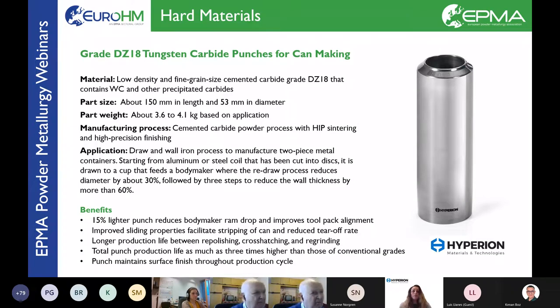This case study corresponds to our cemented carbide solution for manufacturing two-piece beverage cans via drawing and ironing of aluminium or steel cups that are fed into the body maker. Grade DZ18 is our premium cemented carbide solution. It is characterized by a fine grain size and by the presence of not only tungsten carbide, but also other precipitated carbides, the ones that are called cubic or gamma phase.